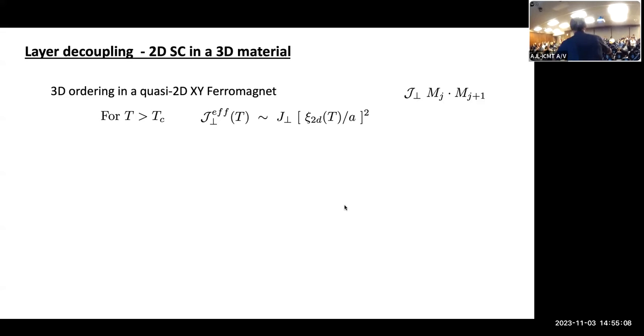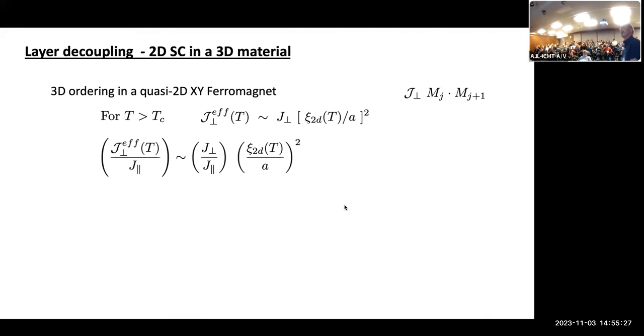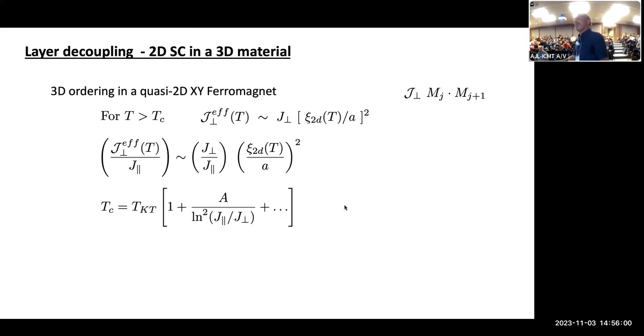You get block spins in each plane. As the correlations in plane develop, you should be thinking of locking a correlation area worth of spins in neighboring planes, and the interplane coupling becomes important when this quantity gets to be of the order of the temperature. So that means that J effective is large in proportion to the square. It's small in proportion to the ratio of these bare couplings, but it's large as the 2D correlation length gets large, so the system should become less and less anisotropic. And, you know, you'll never see 2D Kosterlitz-Thouless type behavior. Your TC will get shifted up by an amount that's, you know, only logarithmically small in the interplane couplings.